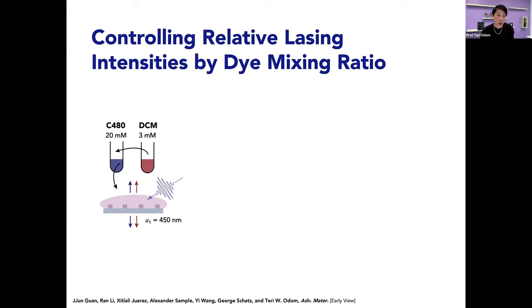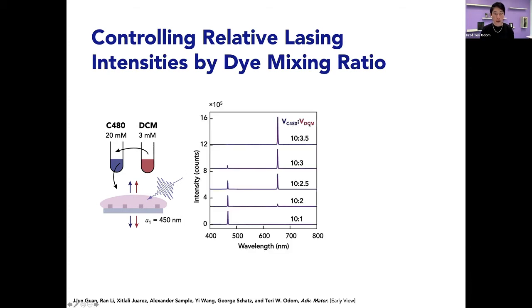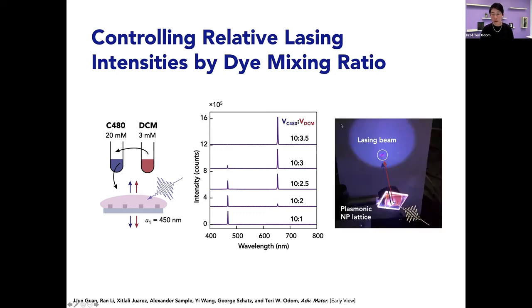But then what we'd like to do is to be able to control the color of the lasing by starting to change the dye ratio. So these are empirically determined concentrations. So we add 3 millimole of DCM to 20 millimole of C480, and then we have a blue pump. And then by controlling the volume ratio, we're able to achieve different relative intensities of the dyes' lasing emission. And so the color that comes out is this integrated color of blue and purple.